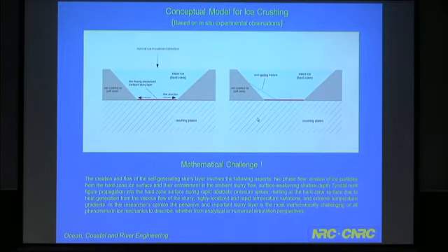So just since this is about math, I don't have much math in this presentation, but I do have a challenge. This is the original drawing that I presented earlier, and I want to focus on the slurry layer and say that the creation and flow of this slurry layer involves several aspects. One is that it's two-phase flow. The second is that there's erosion of particles from the hard zone interface, and that becomes entrained in the ambient flow of slurry. And then there's the surface weakening, shallow depth melt figures that form during the pressure spikes.